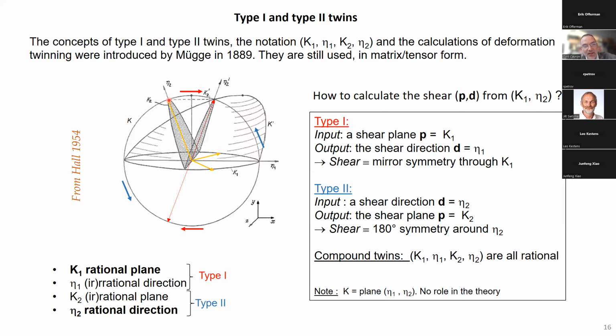Then it's exactly the model of bricks I told you before. I know that if I apply a rotation around this normal here, I can transform this direction into this direction of the same length. This is the initial basis, and this is the final basis after distortion. They look different, but this direction is completely equivalent to this direction. It means that the basis in yellow, the initial basis, and the basis after shear, are in mirror symmetry with each other. So we have created a twin. This is called a type 1 twin because I have chosen the K1 plane. The input data is a plane K1, and the output of my model is a shear direction here, which is called eta 1.